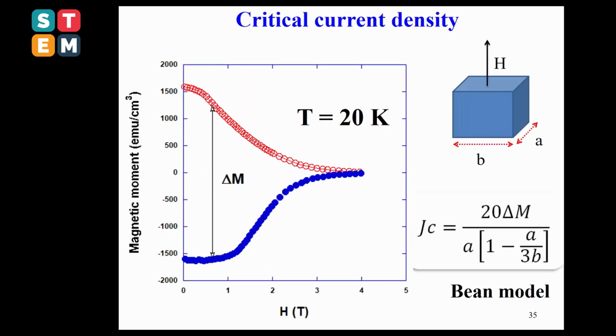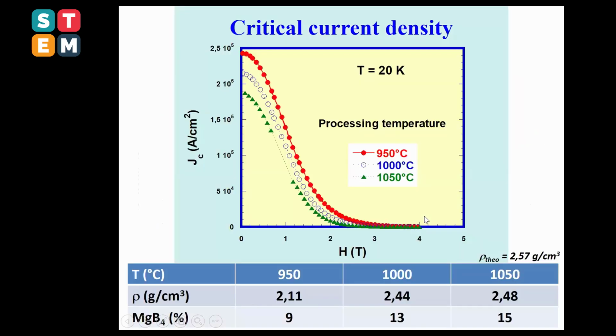But to estimate the critical current density of this material, the hysteresis curve was recorded. This is the magnetic field dependence of the magnetic moment, performed on such small cube samples. You see the hysteresis curve at 20K, and from this, it was possible by using the Bean model to deduce the JC, and the results are shown in this curve.